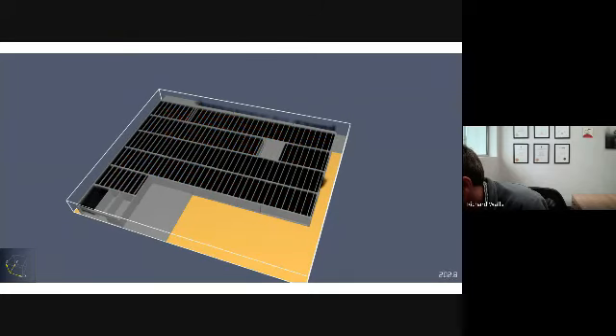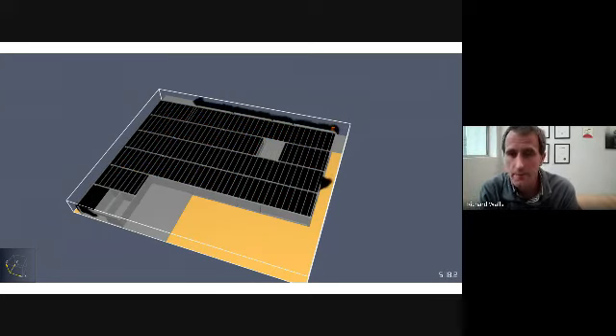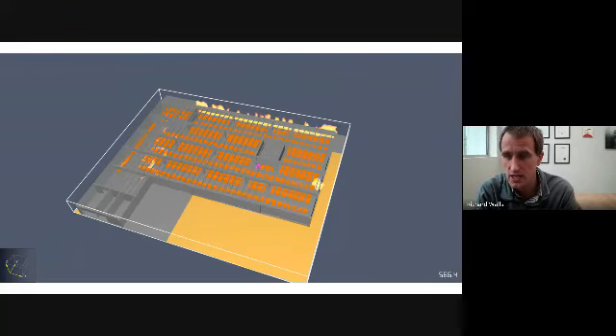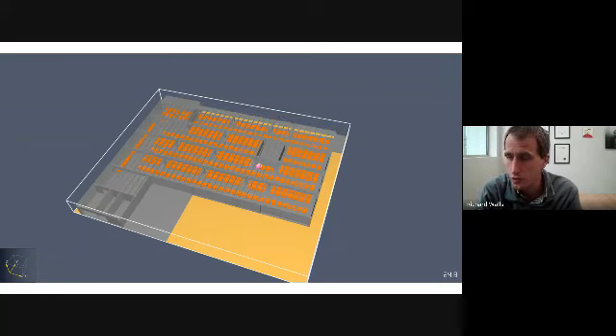Can concrete blocks from bagasse be good? Typically, concrete systems perform well, and with the addition of extenders, bagasse ash, fly ash, ground granulated blast furnace slag, etc., typically it has very little impact on the concrete fire resistance. I haven't checked the most recent research on bagasse ash to see if it makes any difference, but I wouldn't expect it to have a significant influence on your results. Chances are the concrete would be give or take the same.